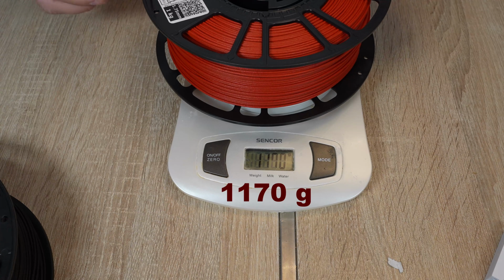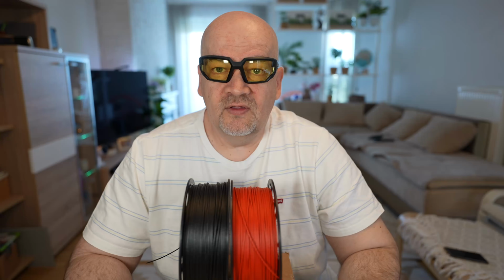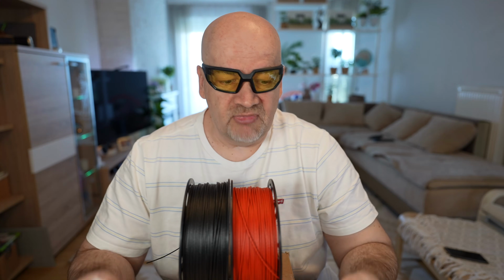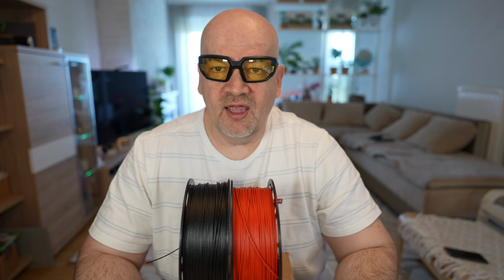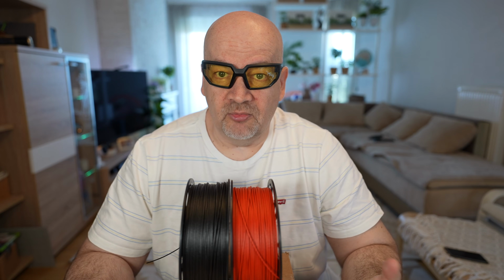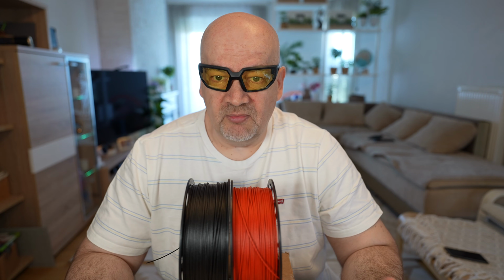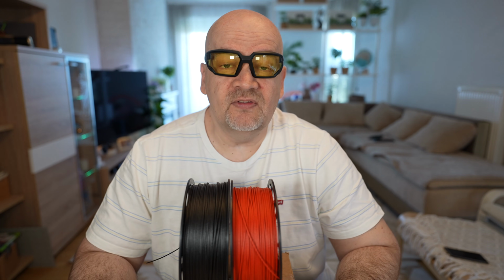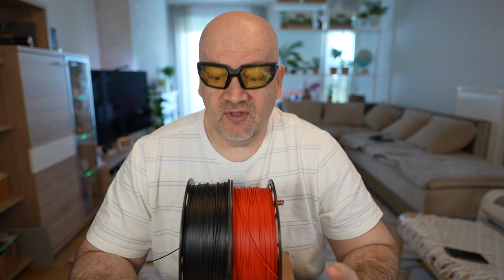1192, 1170, close. Since this was not vacuum packaging, even if they had some desiccant inside, I will dry these filaments before printing, and my drying settings will be for PETG, typically 65 degrees Celsius for 6 hours.